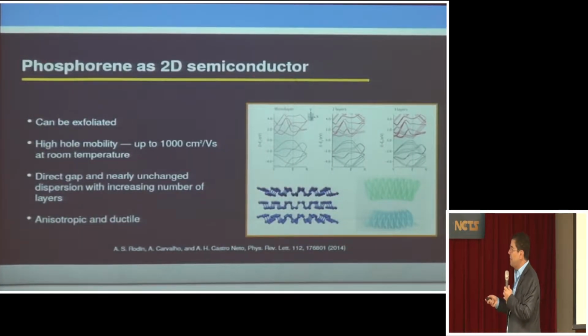So as I said, this material, black phosphorus, the monolayer form is called phosphorene. It has very high mobility. It's a direct band gap semiconductor, and it's very anisotropic. This structure, as you can see, is very anisotropic. The crystal structure is very anisotropic. And this has very interesting consequences, for instance, for optics. So you have dichroism, you have many different things that come from the low symmetry of the crystal. And this can also be used, for instance, in applications.